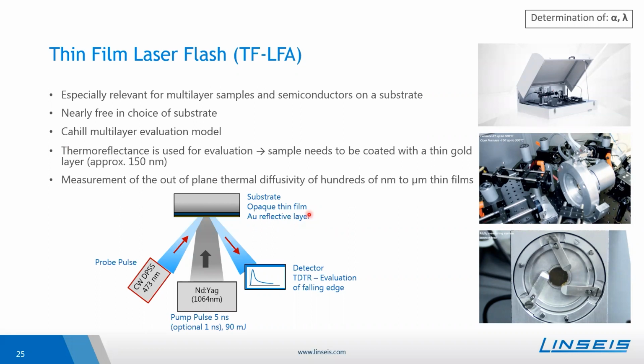The setup in general works similar also to a laser flash, so that there will be a pump laser heating up a small spot on the sample, but we do not use an infrared detector here to find out the response of the material due to this heating, but we use a second laser, the probe pulse, which uses the thermal reflectance of the gold layer to be able to evaluate then the behavior of the complete setup. In the end, we will also have such a falling edge, similar to the classical laser flash setup.